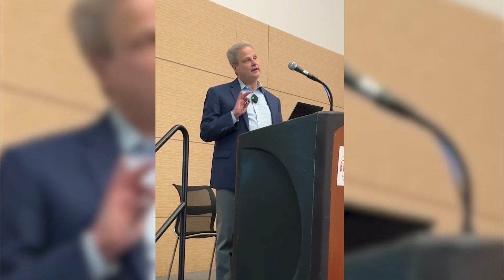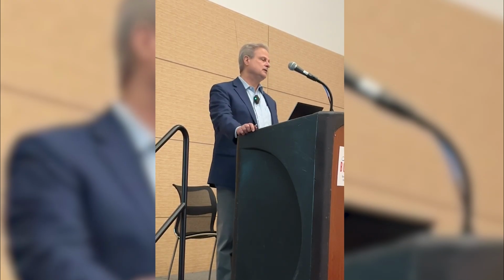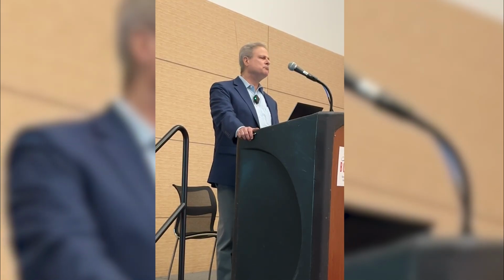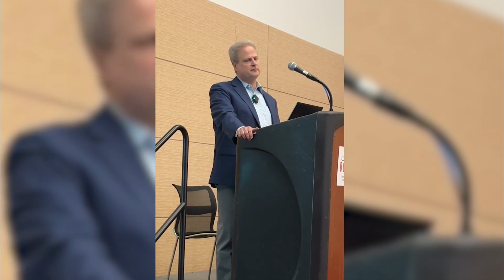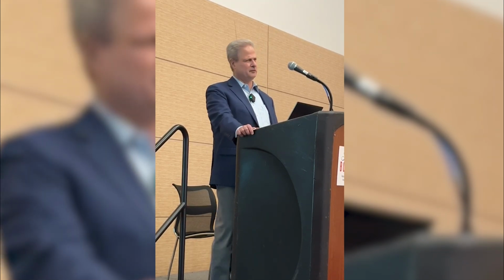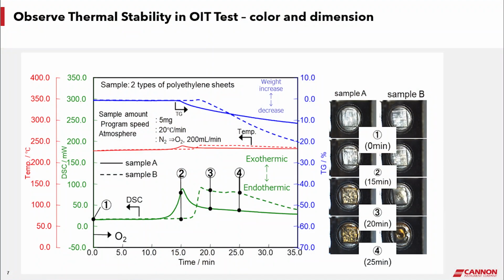But what you can't really get your head around is that samples A and B both contain antioxidant, and they contain usually mineral type fillers, which will fulfill the role of having a high melt viscosity, okay? So you have varying amounts of each, and in sample A, you see a material which has kind of poor oxidative stability, but very good melt strength or melt stability or dimensional stability. Not the case in sample B.